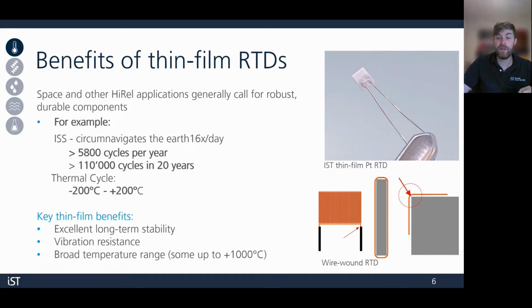At the top right, we have a thin film platinum RTD. The one pictured here is one of the ESCC qualified elements. With these, the platinum is physically bonded to the substrate with the sputtering process, so there's less of a concern for damage from thermal cycling or vibration.